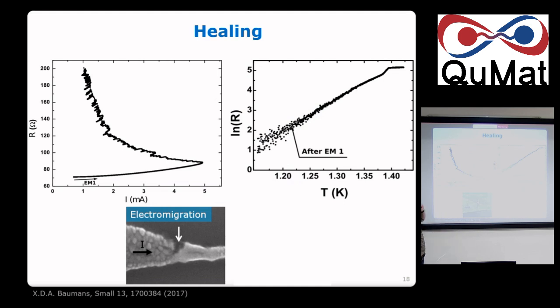Here is another case. This is again aluminum. We started from here. This is once again, you stop here, you come back on the same curve. That's why it's always smooth. This is just heating up. You get there, and then you want to blow up, but you start to fight. And therefore you go up, up, up, and then you see we can get to 200. So it's quite high. It's a few 100%. And then we measure the resistance versus temperature because it's a superconductor, aluminum, with a TC of 1.3 or something. So you see the superconductor transition going. Okay. And then you look at the image and you see this is where I removed the material.